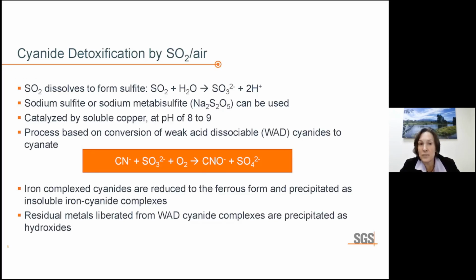SO2 can be dissolved to form sulfite, and you can also use sodium sulfite or sodium metabisulfite. The reaction is catalyzed by soluble copper at a pH of 8 to 9, and it focuses on a conversion of weak acid dissociable cyanides to cyanate, as you can see in the equation, if you're so inclined. Iron complex cyanides are reduced to the ferrous form and precipitated during this process, and any residual metals that are liberated from these WAD cyanide complexes are precipitated as hydroxides.